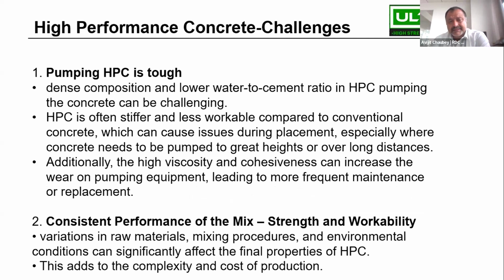Now, what are the challenges? After talking about the advantages, the real problem comes in when you start manufacturing high performance concrete. As I was saying, high performance concrete usually ends up as high strength concrete, and most high performance concretes have a very low water cement ratio. Now, when this low water cement ratio is there, it leads to a very high viscosity in concrete, leading to very high pumping pressure. The pumping of concrete becomes a big challenge.